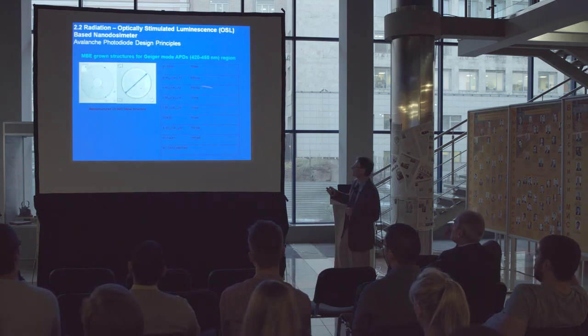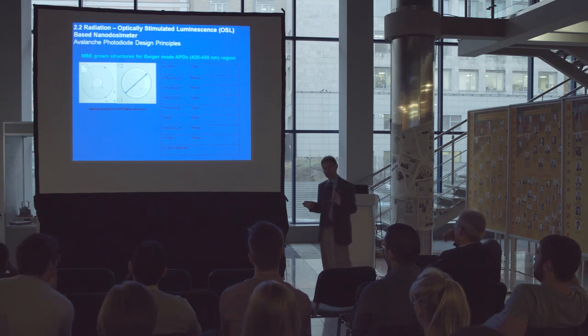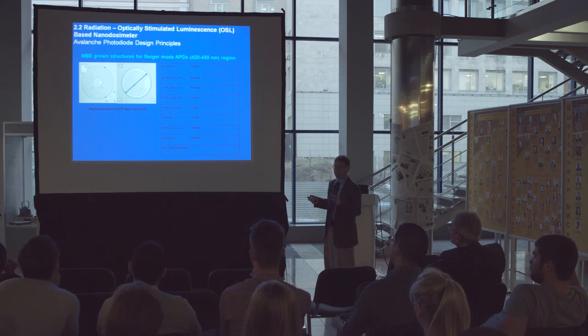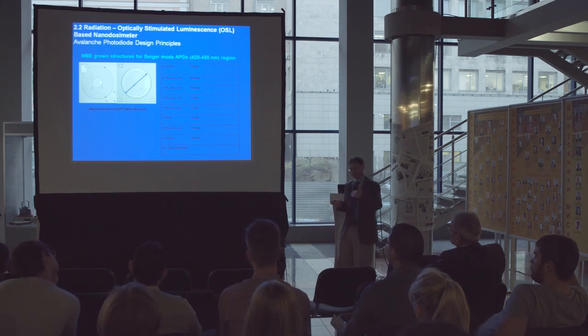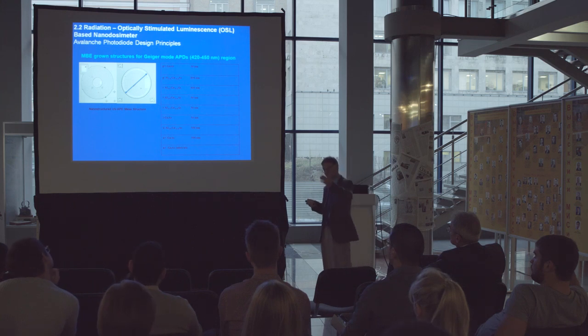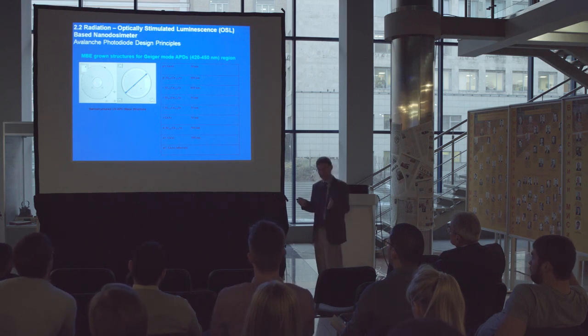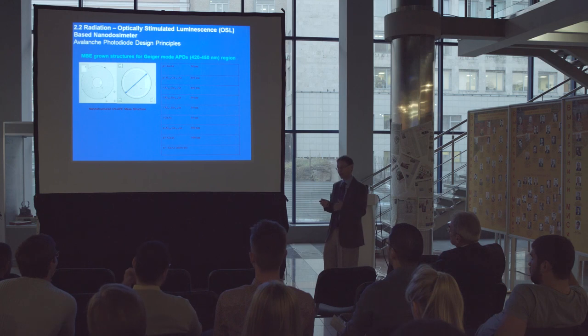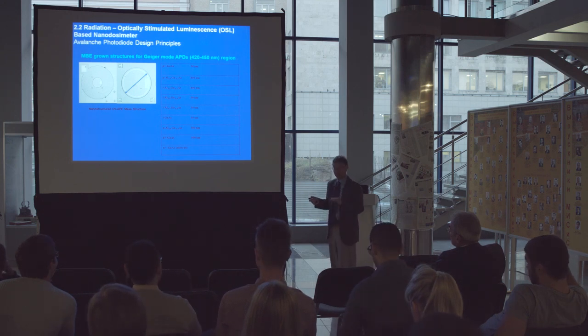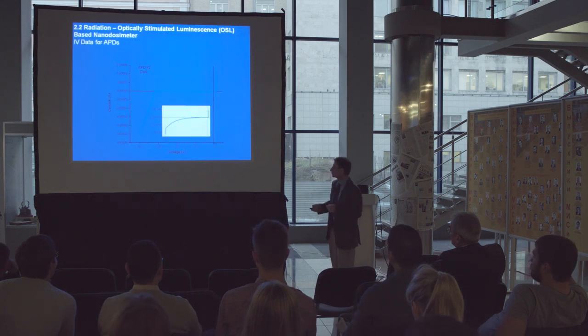The way we realized it is back to the two-dimensional gas-type structures using these PIN structures now, where we've got the separate absorption, the separate gain, and the highly doped region next to the multiplication zone. And size is obviously an issue because we need to get enough signal, right? But we don't want it to be too slow because then you've got a capacitive argument. So there's a balance between the size of the detector, the layer thickness, and everything else.